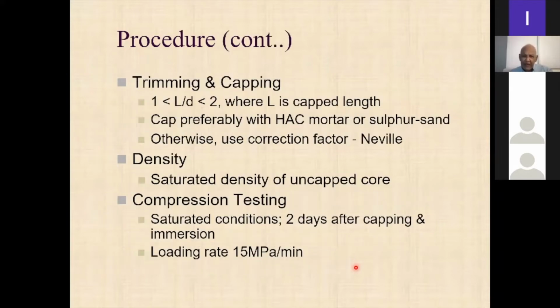So trimming and capping, this length upon diameter ratio should lie between this. Because we are converting to cube strength mostly, it is better if you have length upon diameter close to 1 but greater than 1, right? So you can either do trimming or capping, high alumina cement mortar or sulfur sand. I know people use plaster of Paris sometimes, but then for some of those you have to use these correction factors, right?